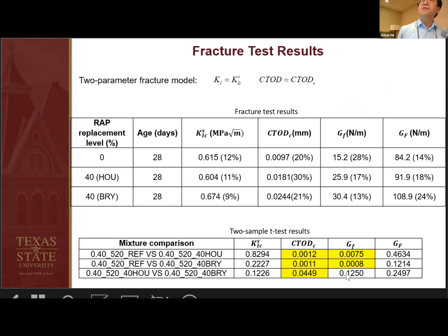For the results, what we found is that by adding RAP up to 40%, you can achieve similar critical stress intensity factor, and the critical crack tip opening displacement value actually improved a lot. You also have higher fracture energy. And statistical analysis verified those improvements were statistically significant.